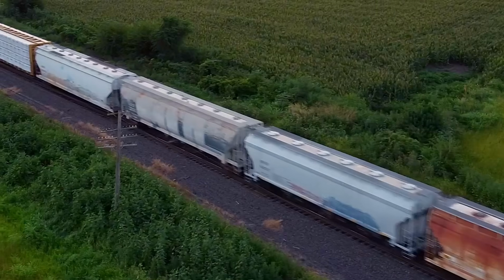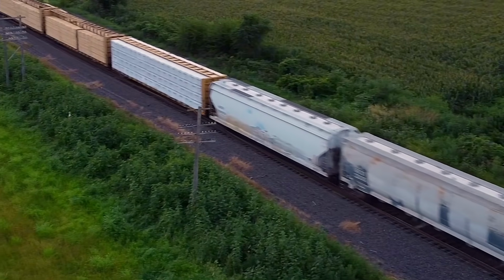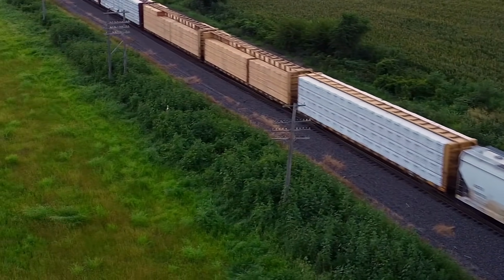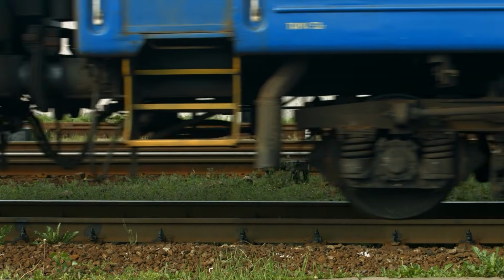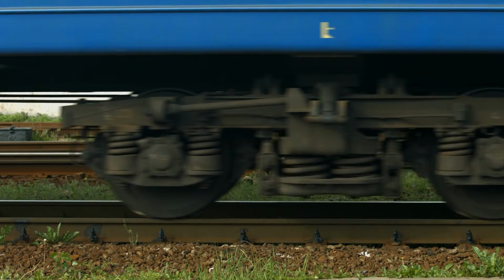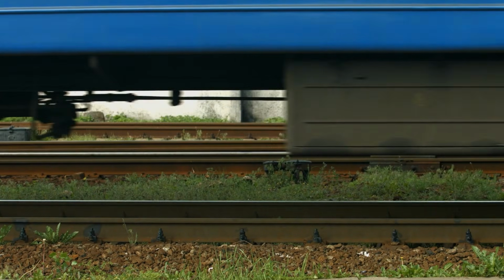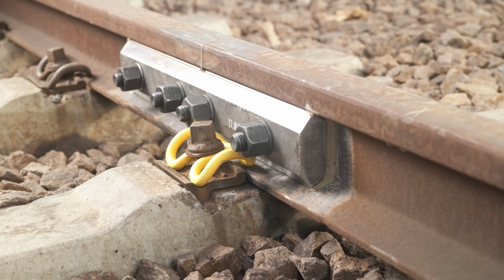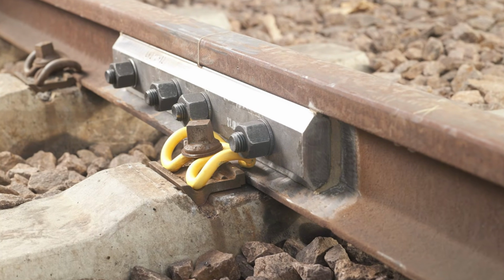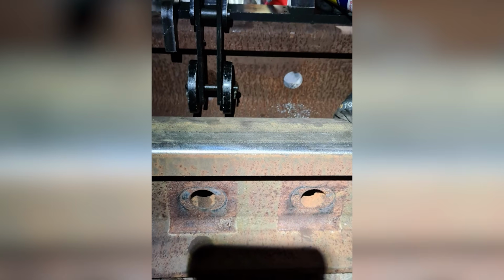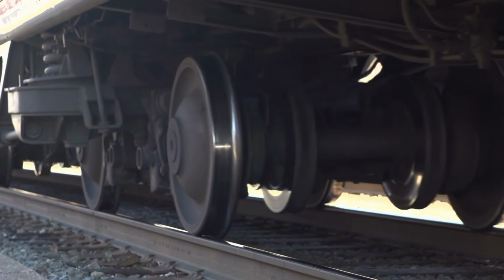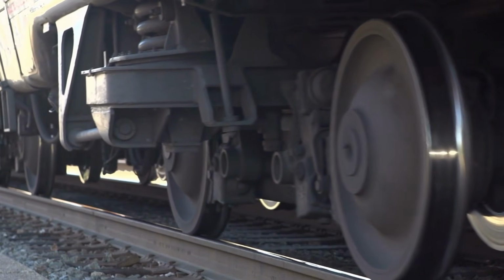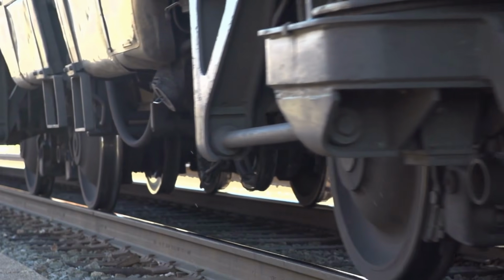While joints have been replaced as the primary way to join rails, they are still found in most railways. They also still do fail, and a failed joint is considered a broken rail as it interrupts the running surface for the train wheels. Given joints are actually gaps between rails compared to a weld, they are inherently weaker. The bolt holes drilled as part of the joints also remove material from the rail, weakening it while creating stress concentrators. The majority of issues with rail joints are caused by movement, of which a certain amount will always happen, given it's a gap in the rail.